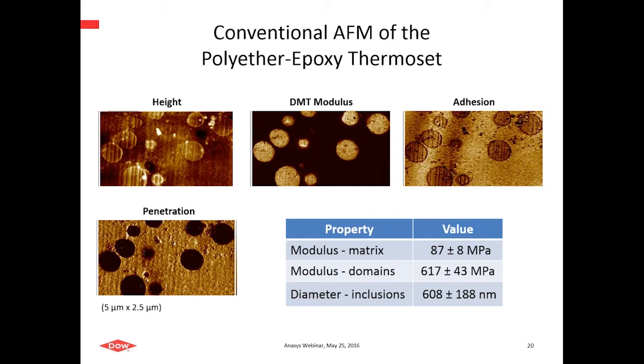Here I'm showing you essentially more or less state-of-the-art mechanical measurements or property maps based on a technique, PeakForce QNM, which is from Bruker Instruments, but other AFM vendors have techniques to do this, and this gives us an idea of mechanical property variation in this morphology. We're well practiced here, and in this case, for instance, we see phase-separated domains that are a micron or submicron in size, and we see that these inclusions or spherical domains are about 7 times stiffer relative to the matrix, and this is based on calibrations and quantitative mechanical measurements.